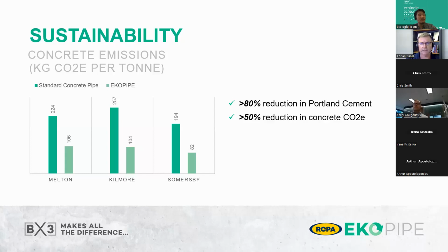Just before we move to the next slide, when we go to make the pipe, obviously we're using steel as reinforcing in the pipe. While a substantial percentage of that steel is recycled material, there is still a CO2e contribution from the steel that goes into the finished product. But what we land on in the finished pipe, which does vary depending upon the pipe diameter and the pipe class, is around a 45 to 50% reduction in CO2e for the actual pipe as produced. And comparing that to EPDs that are publicly available for other materials such as thermoplastics, the EKOPipe CO2e values are actually lower than what you can achieve with a plastic pipe, which is really exciting.